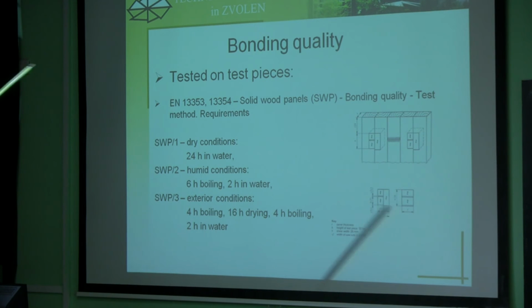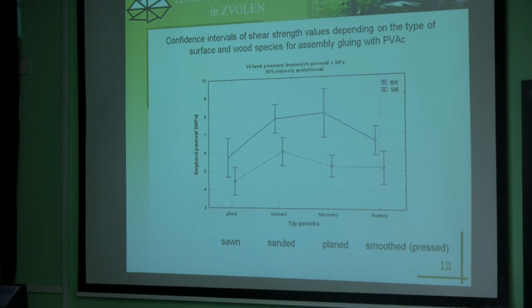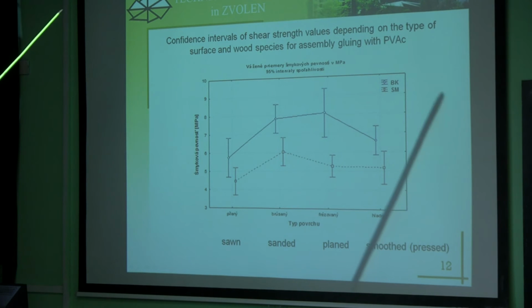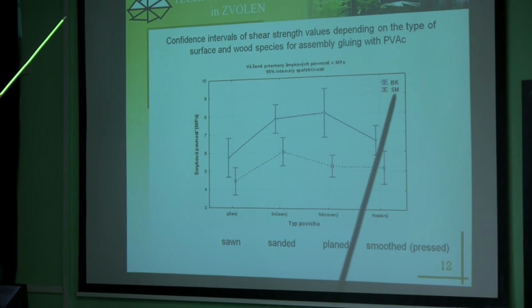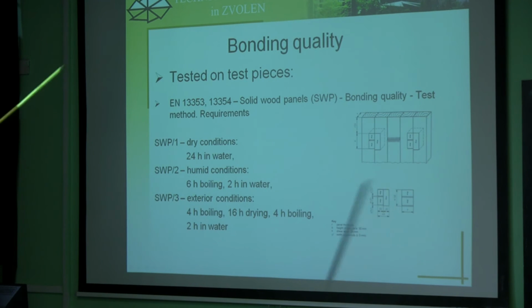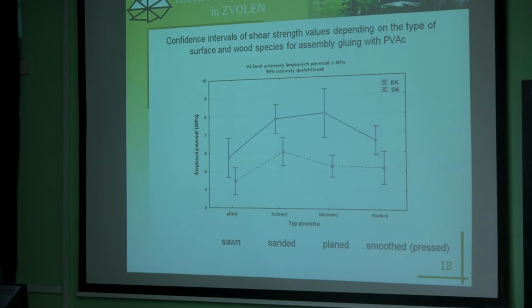And also these test pieces are tested on the shear strength. Shear strength is counted from the dimensions of the sample, the width of the sample, and the height of the sample. For example, we have some tests from my laboratory, and we tested beech wood and spruce wood according to this standard, and we were looking for the relation to the type of surface processing.